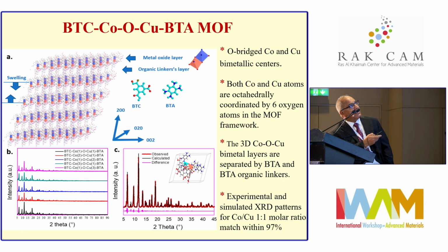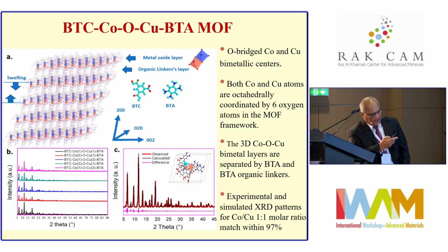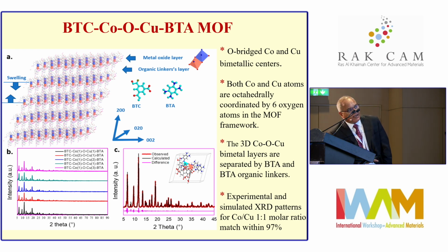So these two ligands, or two organic linkers, are connected in layers above the oxide layers. So we have a bimetallic oxide layer that's blue and red here. Above and below, we have the organic linkers, which can be BTC or BTA. Different crystal structures were calculated with different molar ratios between cobalt and copper. You can see here 1:1, 2:1 and 3:1. The experimental value, the measured XRD, and the calculated one for the 1:1 structure is shown here on the right, and it actually agrees with the calculated structure within 97%. So we are very confident that the measured XRD corresponds to the 1:1 crystal structure, the molar ratio of cobalt and copper.